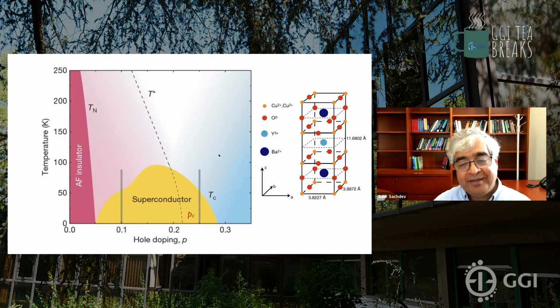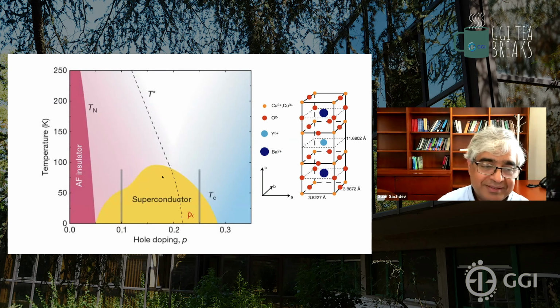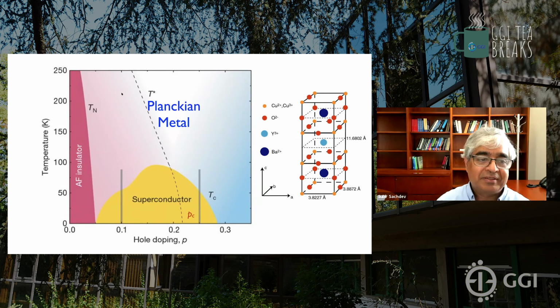Okay, but now let's jump ahead to the high temperature superconductors. This is the famous phase diagram of one of them as a function of hole concentration and temperature. For the moment, I don't need you to know anything about the details of the structure of these materials. I just point out that there have been many, many experiments focused on this regime here, which is at somewhat higher temperatures, let's say 150 Kelvin or 100 Kelvin and above. This is still a very low temperature on any microscopic energy scale, although it's above the superconducting critical temperature. And unlike ordinary low temperature superconductors like aluminum, when you're in this region, it doesn't look like the quasiparticle picture is working.